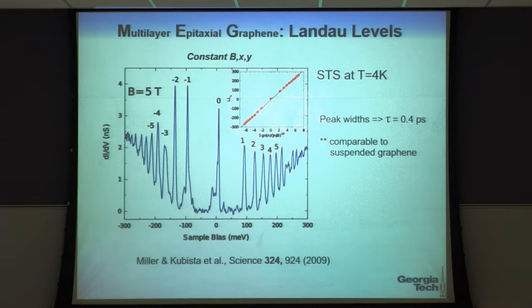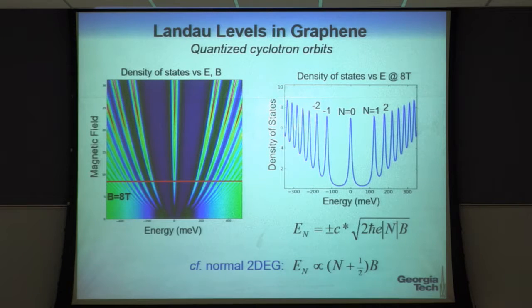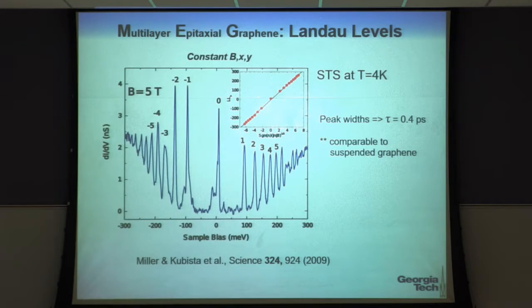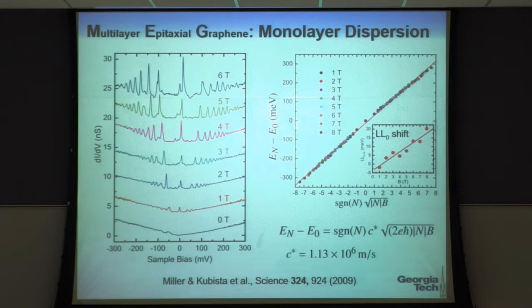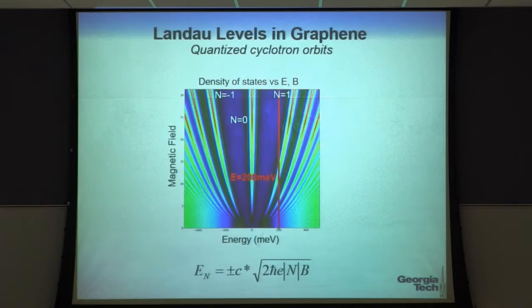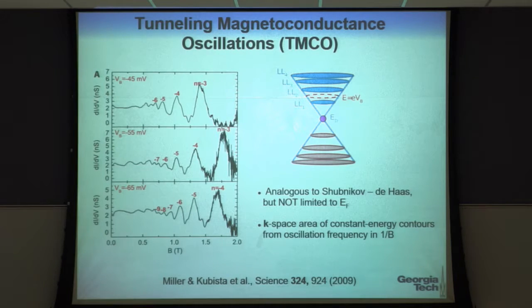We can take a spectrum like this, sweep the voltage between the tip and the sample, and look at the derivative of that, actually using lock-in techniques, and we see these beautiful peaks. And if you plot them as a function of this, or in that functional form, what you find is that they obey that functional form very, very well. And if I go to many different magnetic fields, they obey that functional form extremely well. And, in fact, you can then measure the slope of the band structure, measure the band structure itself. So that was basically measuring this slope.